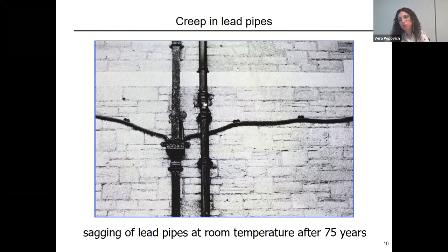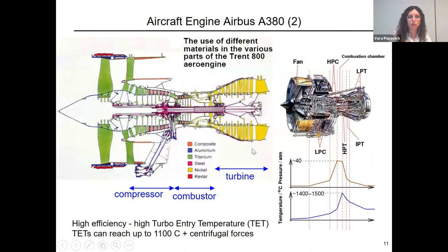Here, when we talk about creep, and we'll dive into this concept, temperature is important for creep to consider. In general, we say that for crystalline materials, creep is important above 0.3 of the melting temperature. So, for example, for nickel alloys, it depends on the alloy. It already becomes alarming above 900 degrees, but we'll see that there are superalloys which are more resistant than the others. For ceramics, it's a bit different. It's 0.4 to 0.5 of the melting temperature. So for example, for alumina, aluminum oxide, it's close to 1,000 degrees that creep should already be considered.